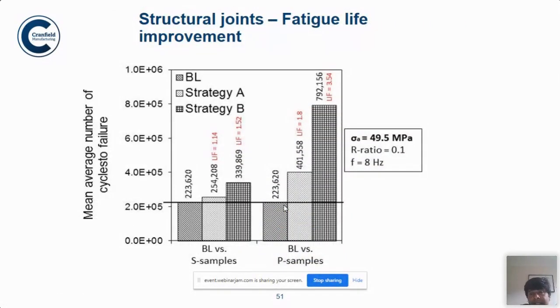Now I will explain this one. You will see here, BL stands for base level, so base level versus S samples. As you can see here, the S samples are the stripes. You can see the life improvement factor that you achieve using stripe is a maximum of 1.52. Whereas in P samples, peening, the life improvement factor you achieve is almost 3.54. So almost 4 times life improvement you can get when you do a good peening in this configuration.